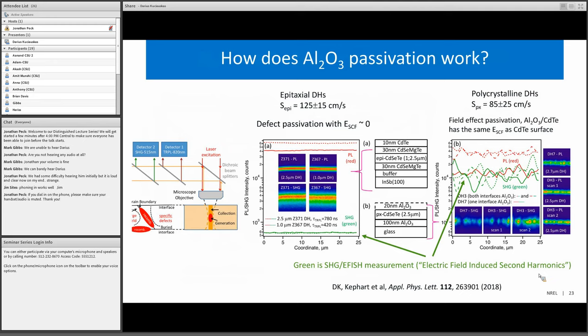When we measure the polycrystalline materials, however, the electric field in the material stays about the same whether the alumina is applied or not. So the alumina passivation appears to be working by the field effect mechanism rather than the defect passivation mechanism. Being able to measure not only photoluminescence intensity and lifetime, but also the field strength in the same correlative measurement is actually very useful in being able to understand the mechanisms of passivation, whether that would be with alumina or in some other material systems.